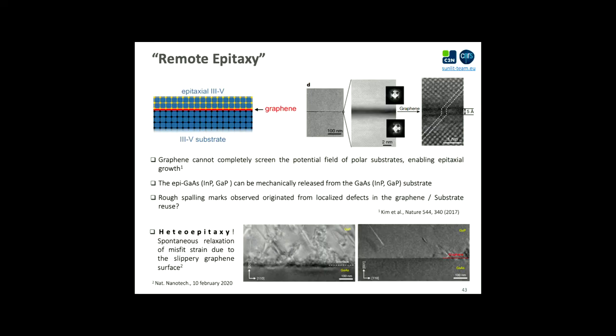So what they did recently, about 3 years ago now, is this remote epitaxy, and the idea is slightly different. You take this III-V substrate, you cover it with one monolayer of graphene, and then you start the epitaxy. The claim here is that the graphene only partially screens the polar interaction from the substrate, so the substrate can still direct an epitaxial growth of this layer, because it's a sort of tunneling of information from the substrate.